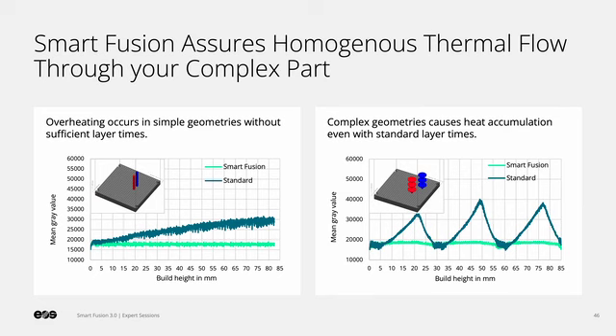To systematically analyze the potential effects of such features on the microstructure, we use a test geometry that generates severe heat accumulation. It consists of three cones with an overhang angle of about 45 degrees stacked on top of each other. They are connected by small cylindrical pins, which also act as thermal bottlenecks. The part may look deceivingly simple, but is actually a rather challenging build. The geometry is very much inspired by previous studies on the subject, and multiple researchers have used similar geometries in the past.